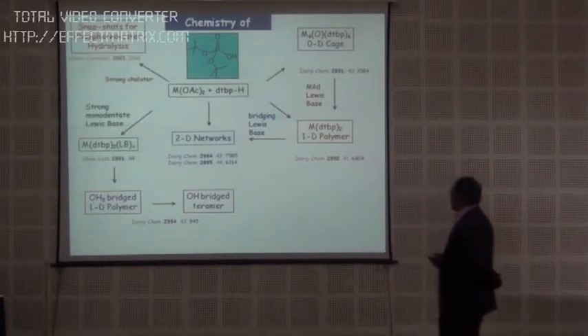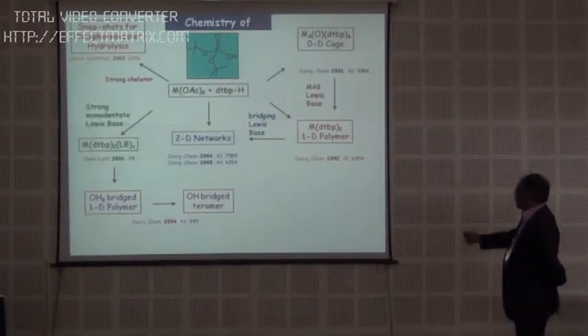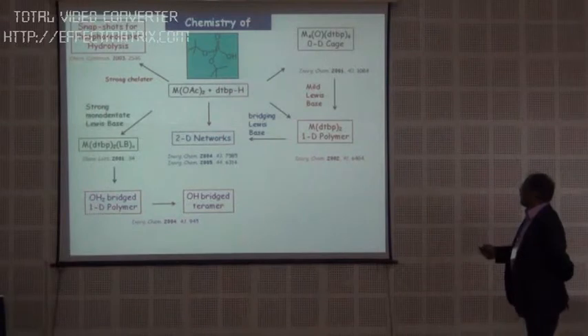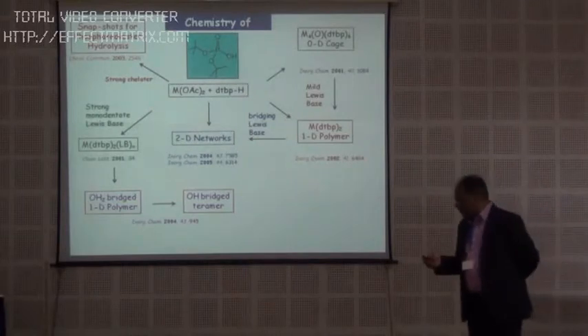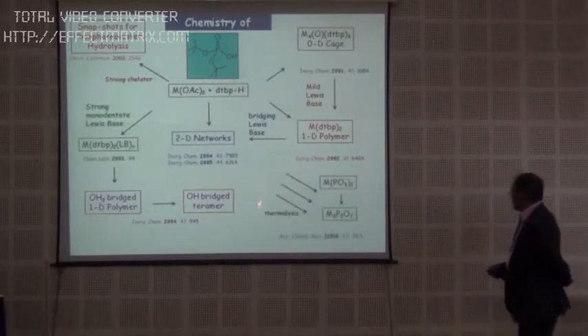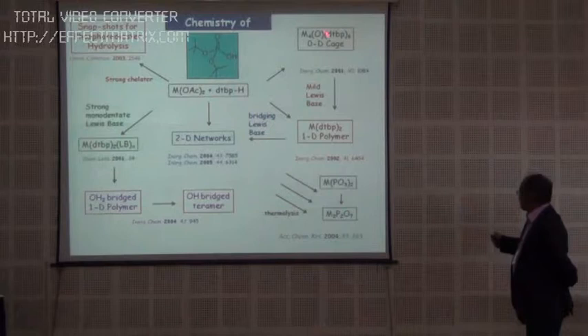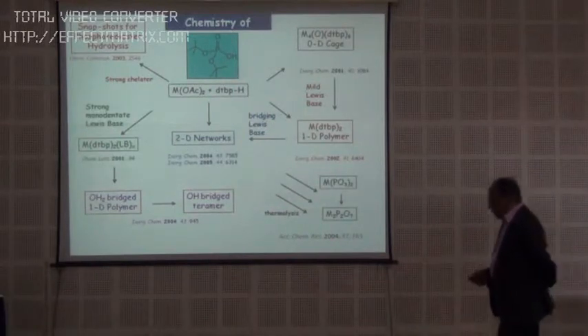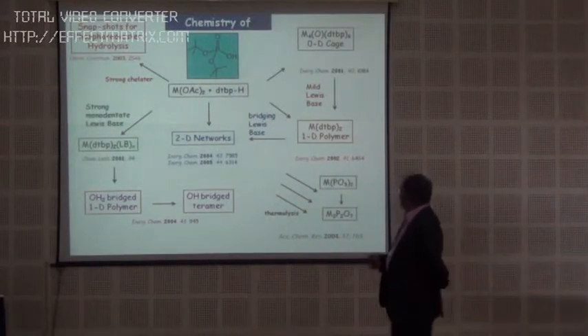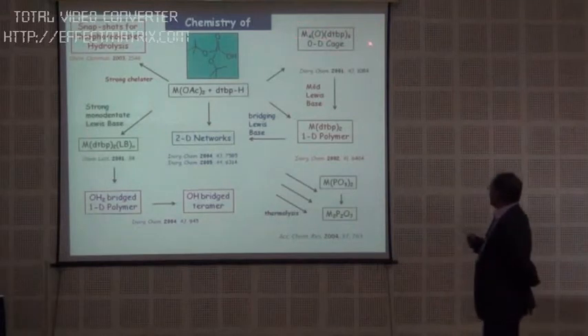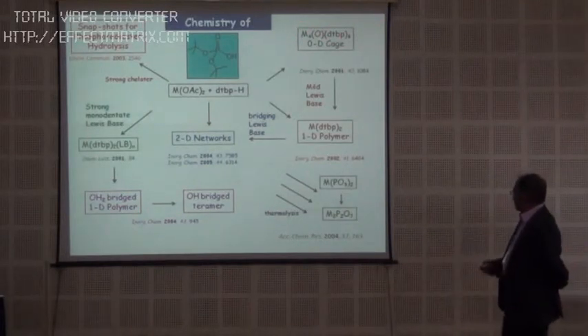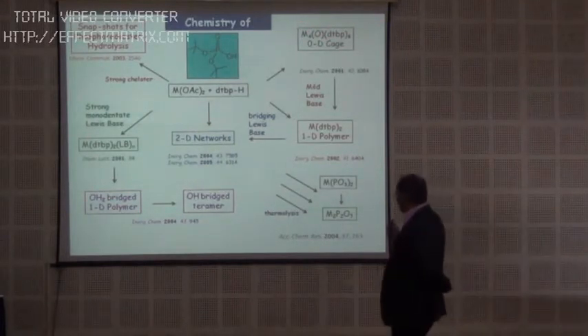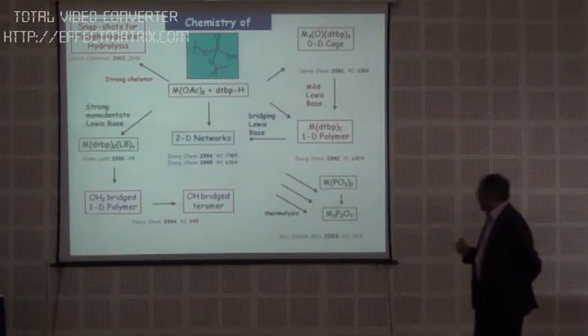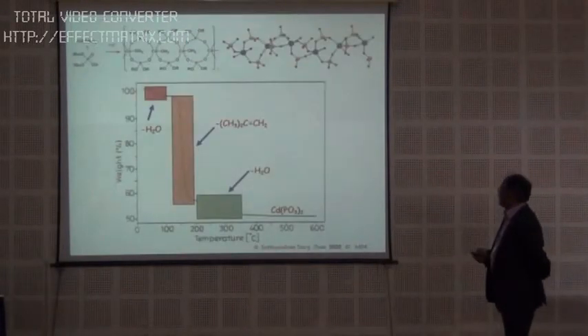One common theme running across all these materials, don't worry about what they are or what structures they are, is that they are pretty much inorganic compounds with only 2 organic groups, namely ditertiary butyl groups, which undergo facile thermolysis. After making these compounds, you can easily thermolyze and make a material of your choice. Depending on the metal to phosphorus ratio in the starting material, you can get a variety of phosphates. And since you work with molecular systems, your thermolysis is clean, neat, and you get only one material.